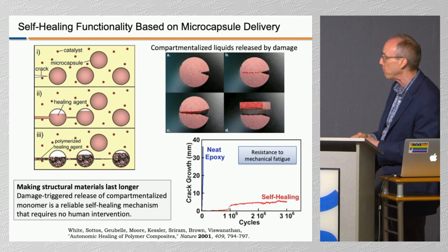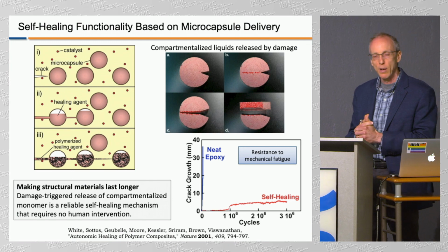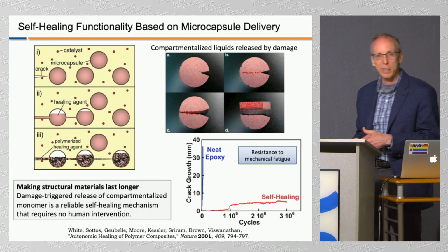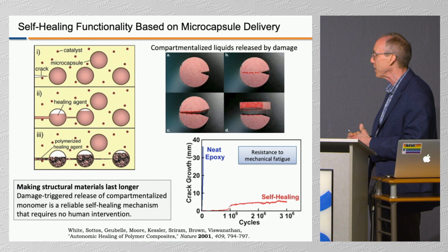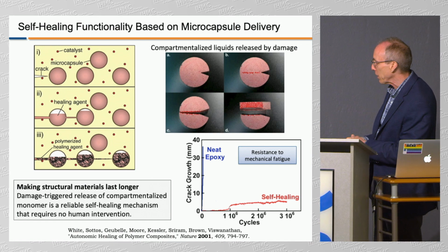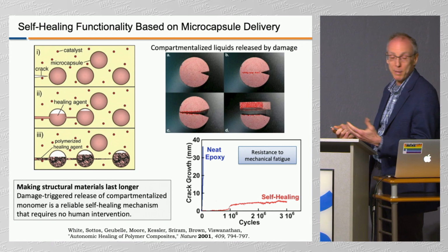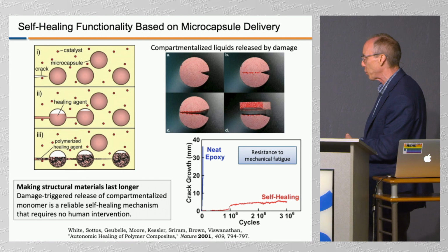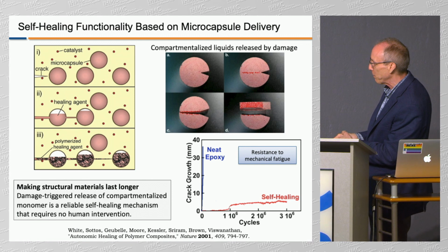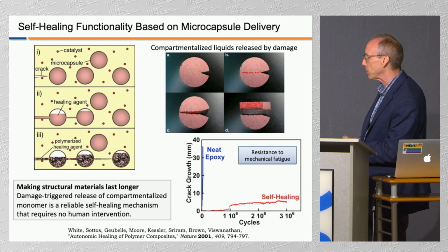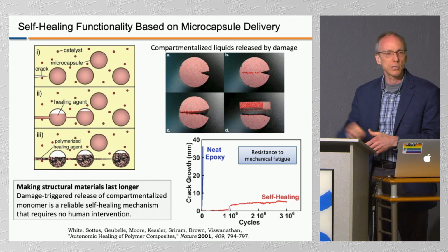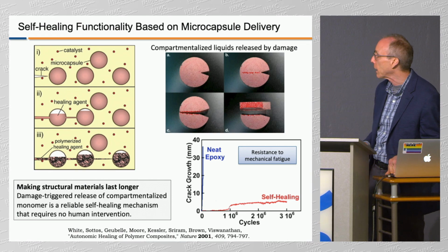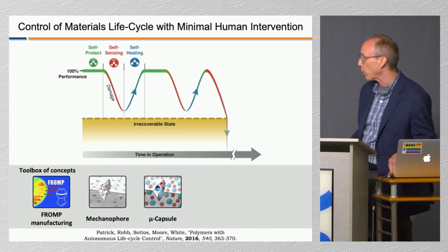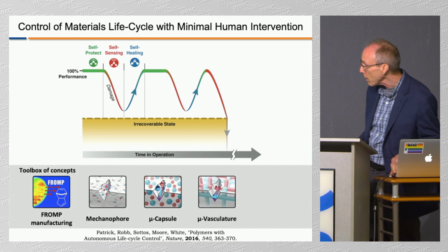So you'll notice it's millions. These experiments take a long time. Fortunately, our students still graduated in reasonably like 4 or 5 years. But they do take a long time, oscillating at about 5 hertz to get 1 million cycles. You can do the math yourself. Here's the self-healing material. You can see it started to undergo damage. The crack was growing, but then it stopped because of the self-healing capabilities.